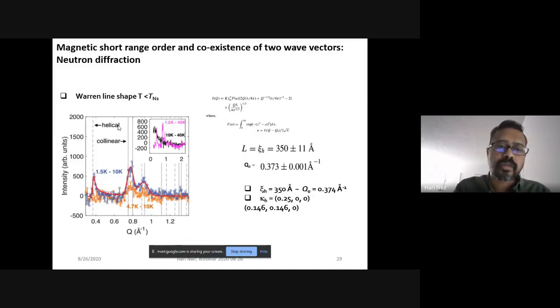Now, with these broader peaks, we are able to determine two characteristic length scales: one, that of a helical structure at low Q, and one, a collinear structure at high Q. The red line that you see is actually a complicated function, which is given on the right-hand side. But all it means is that it mimics what is known as an excitation in a metallic liquid. So it's developed for some sort of liquid-like systems.